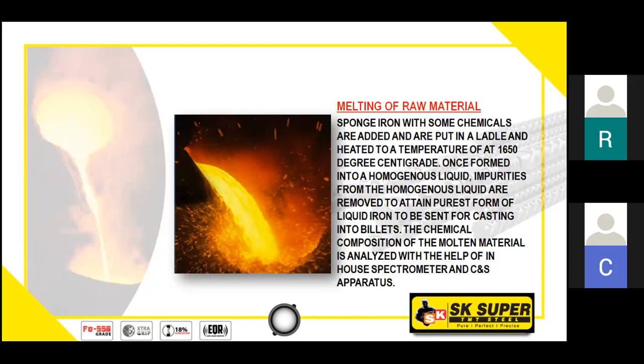Once the perfect chemistry is achieved, the sponge iron goes to a big furnace which we have installed of 15 metric tons. The 15 metric tons of sponge iron is melted. It is basically like a bucket, what you saw in the video. It is heated to a temperature of 1650 degrees. Again, a small sample of this 15 metric tons is taken and the chemistry is checked, because between a 5 kilo sample and a 15-ton sample, there may be variation in the sponge which any plant procures. So once this 15 tons, or one lot of steel, has its chemistry assured, then